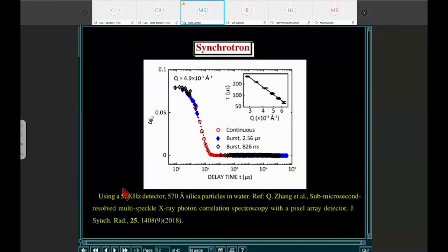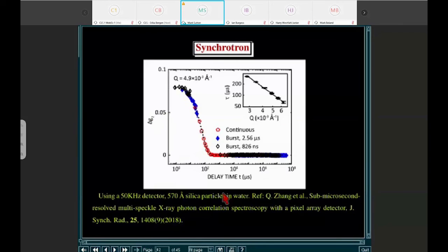which can be run in single photon counting mode at 50 kilohertz. As a matter of fact, in bunch mode, we can get of order 16 patterns with even faster time constants. Here's the measurement of a silica particle in, I think, liquid water, where the time constant is, if you can read the graph at the bottom here, of order 50 to 100 microseconds. The first data point in the red curve occurs at 20 microseconds, and that's taking full frames at 50 kilohertz, so we can do that.